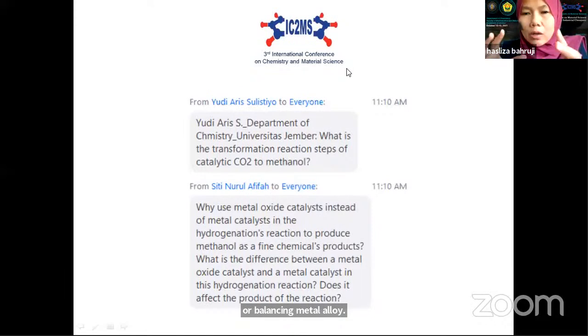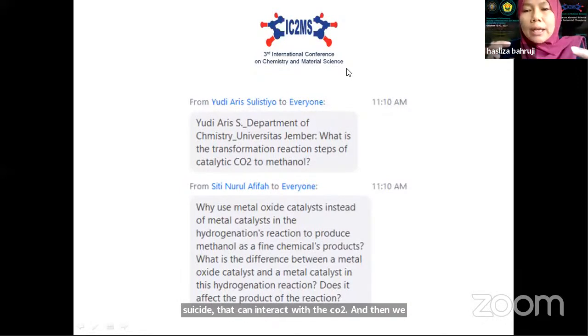Normally, metal oxide provides oxygen vacancy sites that can interact with the CO2 and weaken the bond, and it will be much easier for hydrogen to reduce them. So this is the different role of metal and metal oxide support. Does it affect the product of the reaction? Yes, it affects the product of the reaction.